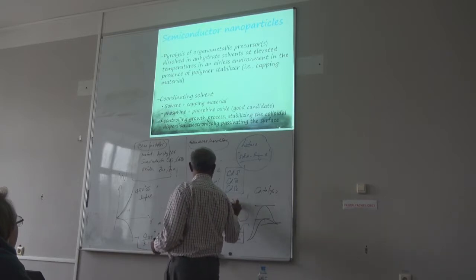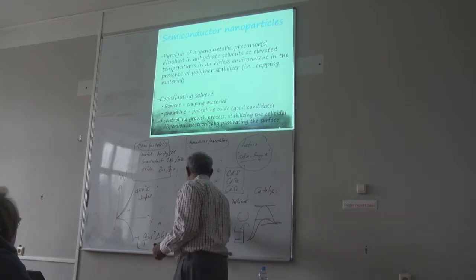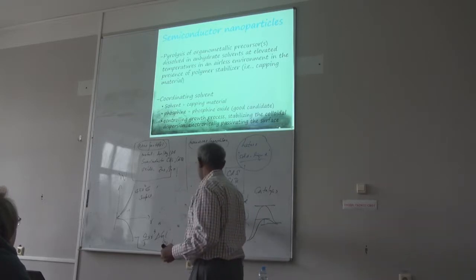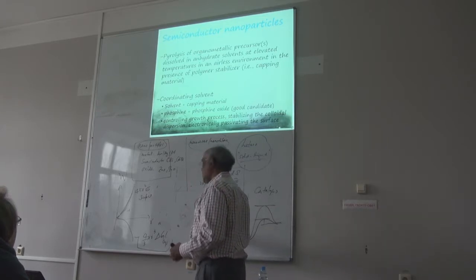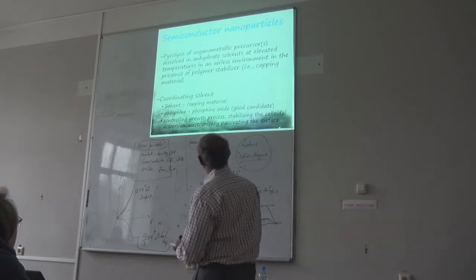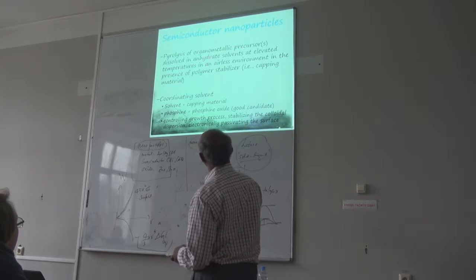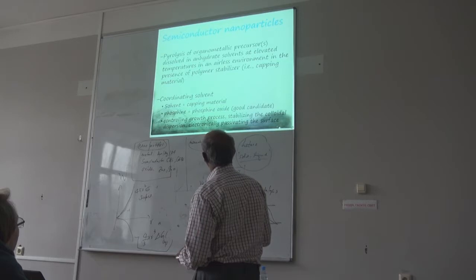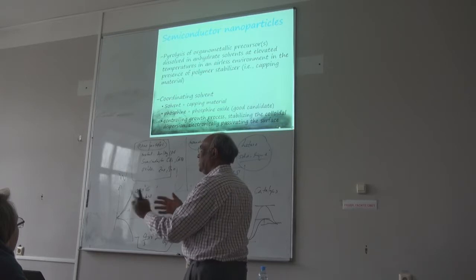say, telluride. Dimethyl telluride. So that means you have tellurium, you have two methyl groups, right? So then you have some tellurium attached to this one. So this is organic with the metal. This is a metal organic compound. So you have to have that metal organic precursor. Then you dissolve that one in some solvent and heat it in an inert atmosphere. Sometimes you have to use some kind of stabilizer. Always you have to have a stabilizer to keep it from agglomerating.